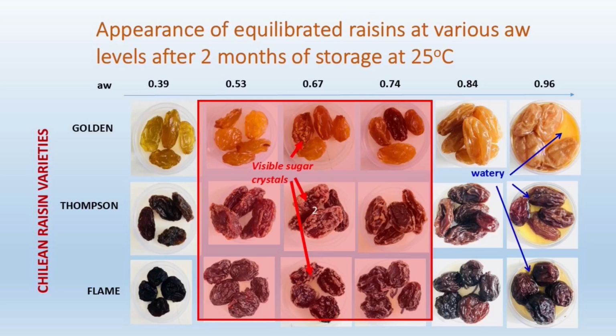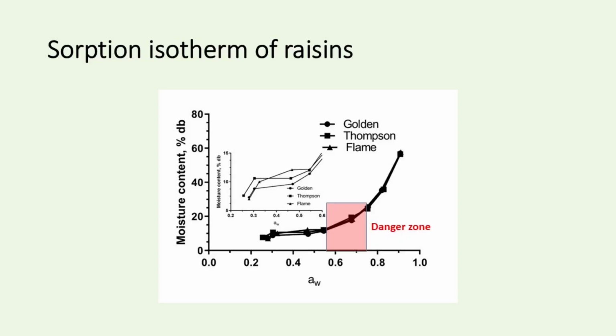So then what we did is we stored the samples at different water activity conditions and observed the sugaring, or the crystallization of the sugar, on the surface. You can see we took 3 varieties: golden, Thompson, and flame. You can see between 0.53 to 0.74, that region, you have crystallization of sugar. You can generate a similar situation to what you were noticing. So that means the water activity is a very critical factor. That's the danger zone where it may happen.